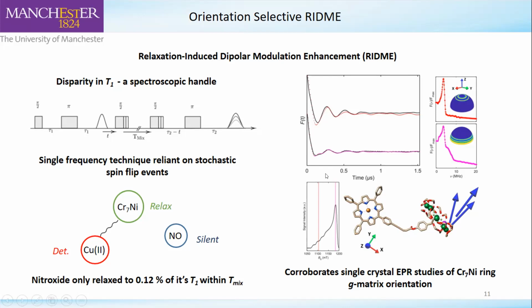fits. We can actually go back to our model and see which orientation is giving us these best fits. And we were able to corroborate single crystal EPR studies of the chromium-7 nickel ring's g matrix orientation, in particular the gz component, which is represented by these blue arrows, which has been suggested by single crystal EPR to be perpendicular to the plane of the ring. So that was really quite nice.